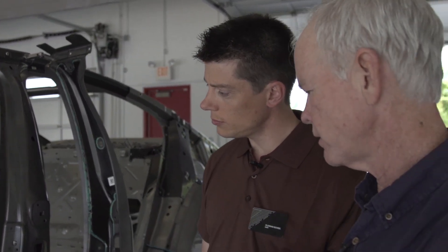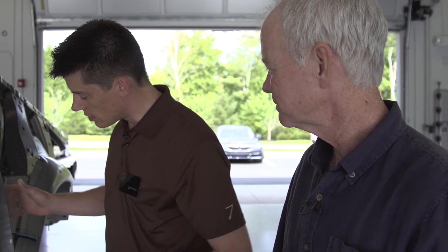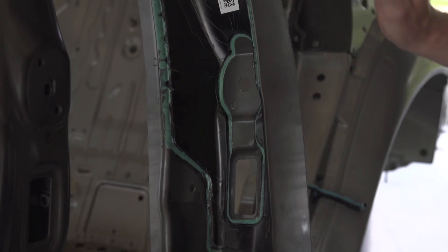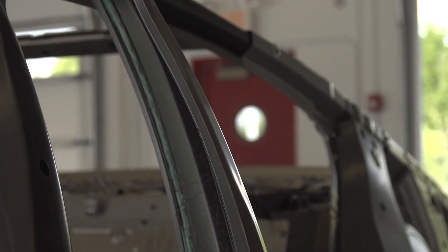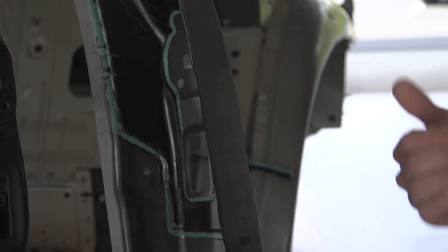I think that's an important point that you just made. It's not just the lightweight carbon fiber — it in turn allowed you to reduce the gauge of the steel and get more weight savings as well. Basically, that's where the weight savings come from. You can see this also here in this B-pillar. We have that carbon fiber inlay here, and due to this, we were able to reduce the thickness of this B-pillar, which is a hot-formed sheet metal piece, and so getting the weight reduction.